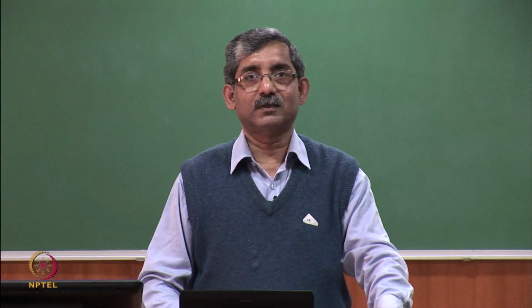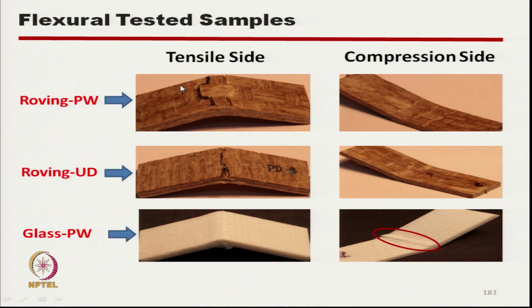Now, this is the roving plain woven fabric, where we have already discussed there are multiple places of damage. This is unidirectional roving and this is glass PP plain woven. Interestingly, for the glass PP plain woven composite, at the compressional side when we bend during flexural testing, delamination takes place, but this delamination is absent in the flax polypropylene composite, which is a very good sign as far as the flexural characteristics are concerned.